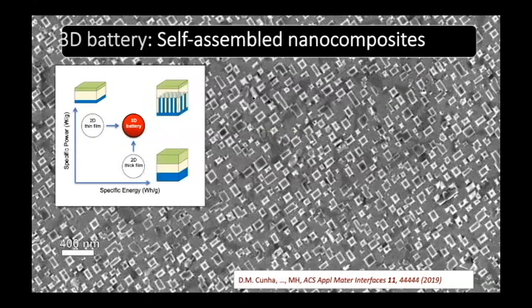One interesting example that is being looked at is again here in the scheme, where you can see the specific power versus the specific energy. You can well optimize a thin film battery, for instance, in terms of specific power, so you need a large area. Or in terms of specific energy, you need a larger volume of the anodes and the cathode. But if you have a different geometry, called the 3D battery geometry, where you get columnar growth between the anode materials and the electrolytes, you can have both of them.